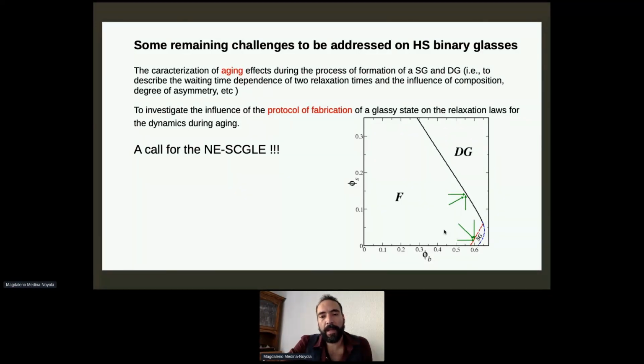the theory predicts, as Marco was emphasizing, for instance, the importance of the kinetics of structural properties, or properties associated to the structure of the system, with waiting time. And as it happens, the theory predicts different structural evolution for a binary mixture approaching these transitions upon quenches, for instance, and predicts different kinetics at the structural level for the system approaching each of these states by different routes. And without solving the equations, one can realize that this might lead to different relaxation laws for the aging of the dynamics. And it will be very interesting to explore this problem.